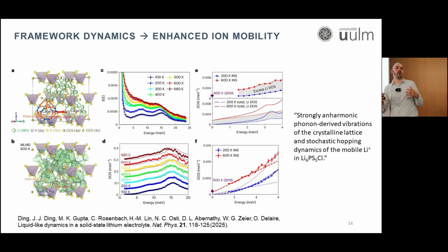So some of you that work on solid electrolyte systems might be familiar with this kind of field. Usually these kind of materials here are shown as a very crystalline structure, but in fact if you record these materials at ambient temperature, you probe them with powder X-ray diffraction, you will recognize that they show amorphous features. We have seen at several talks today actually that upon charging, discharging, some cathode or even electrolyte systems lose long-range order. So that comes in again with not only losing the long-range order but also complete changes in the mechanical properties. For example, the mechanical rigidity is strongly reduced when the crystal lattice is losing this long-range order.